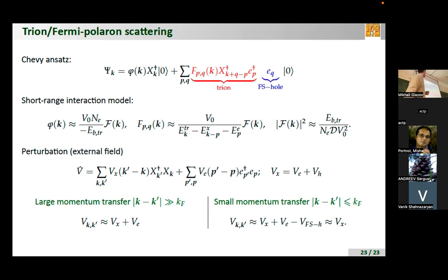Here, the regime studied by Suris and in the physics of Fermi polarons is a different regime. Here, the Fermi energy is much smaller than the exciton binding energy, and it is typically not too large compared to the trion binding energy. And then you can present the many-body state of your system in the following way. Zero here is vacuum, meaning the Fermi sea, when you have the occupied Fermi sea. So exciton and unperturbed Fermi sea, plus exciton in some other state and an excitation in the Fermi sea.